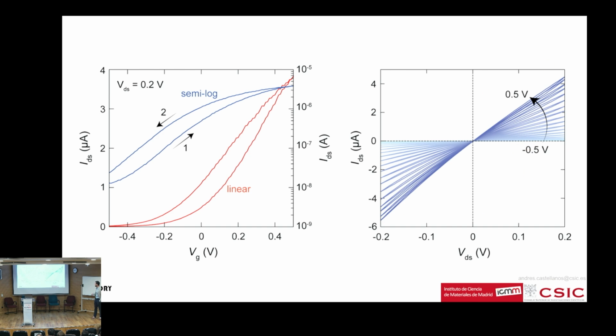The transfer curves are almost textbook, with a little bit of hysteresis, but almost tiny, despite the fact that these devices are working on this rough surface. I want to stress this, because in many papers they test the transistors on the flat surface before peeling off and transferring to the rough surface.